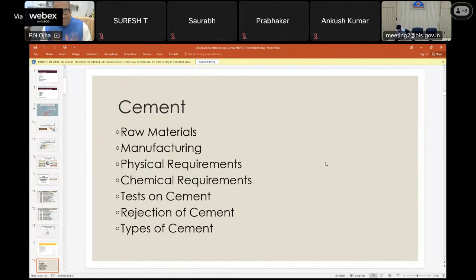And as I said, the cement should perform. So we have certain physical properties like consistency, which means the quantity of water to be added in terms of percentage. Then setting time, initial setting time, final setting time, then fineness, then strength, 3 days, 7 days, 28 days strength. And cement should not be adverse to soundness, so it should be sound. So the soundness test, Le Chatelier soundness and autoclave soundness, and their values are there in the specification. So all these are the physical properties.